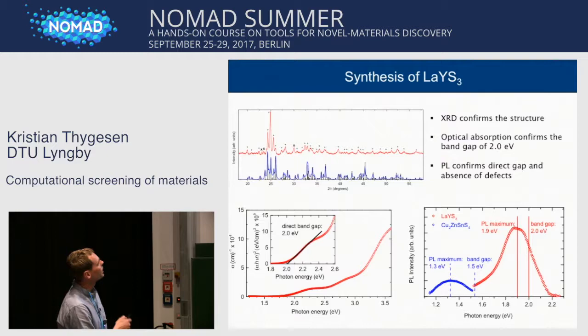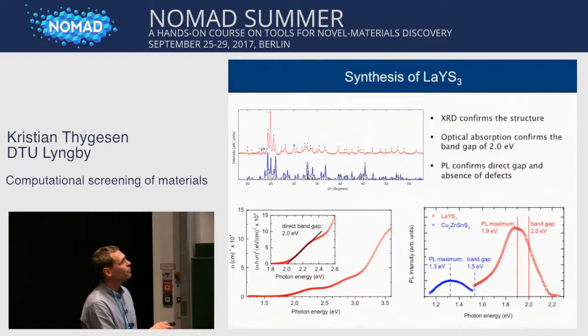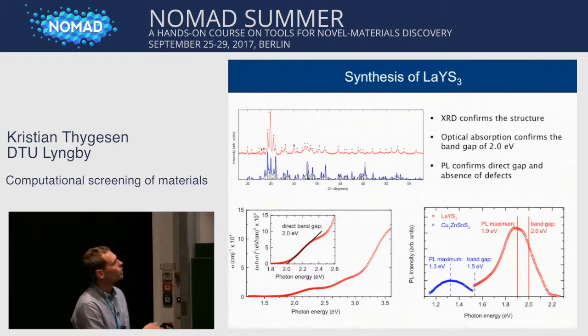And using XRD, they confirmed that the structure they obtained was actually the one we had predicted. And they confirmed that the band gap from the absorption spectrum here was 2 electron volts. And they also confirmed from the very strong photoluminescence peak here at close to 2 eV that this was a direct band gap material as predicted, and that defects were playing a minor role. Because if you have too many defects here and you have states inside the band gap, then the photoluminescence peak will be dramatically lower. So the intensity of this photoluminescence peak strongly suggests that it's close to being a pristine semiconductor. There might be defects, but they don't introduce localized states in the gap.